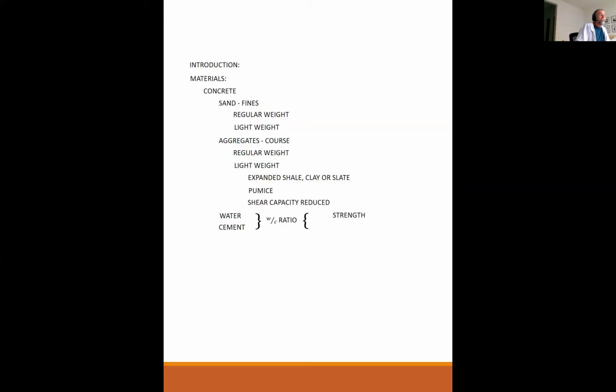As opposed to a water cement ratio of 0.4 to 0.45, which is structural concrete, maybe 4000 psi, 3500 psi. When you get into the 0.3s, 0.35, 0.33, now we're talking about real concrete, 5,000, 6,000 psi. And you really can't get too much lower than 0.3. Below that threshold, you actually don't have enough water to fully hydrate the cement. So that's really kind of the extremes. It's 0.3, 0.35 on the high strength side, all the way to 0.5, 0.55 on the low strength side.